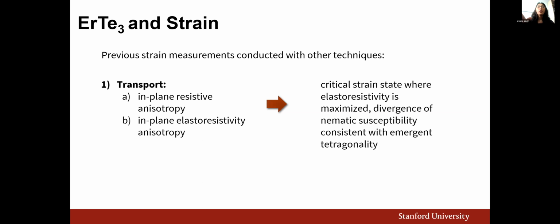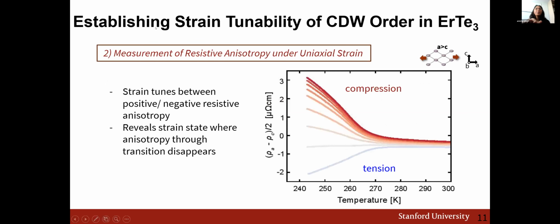All right, so on this slide, I'm just plotting the in-plane resistive anisotropy as a function of temperature for different offset strains. And what you can see is that as we pass through the CDW transition, which again is at about 268 Kelvin, the resistive anisotropy flips between positive and negative values, depending on which axis is hosting that CDW order, which we can control by strain. So consistent with what we see in our XRD data.